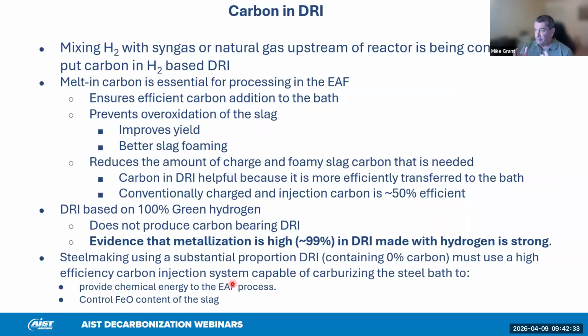So, of course, there's been a big debate on the importance of carbon in DRI. Keep in mind that the carbon in DRI comes in the form of iron carbide, and iron carbide doesn't melt. And so it dissolves, and so from a melting point perspective, it doesn't really help so much. The secret is to charge the DRI continuously at a rate that it could effectively be melted by the arc.